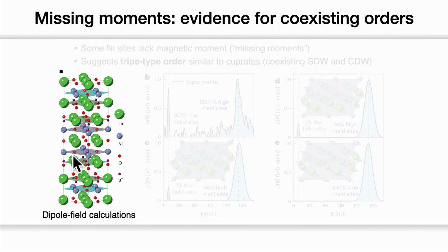Here shows the structure of the LNO superconductor. We put muons, this is a muon in purple, at some places in the material and perform so-called dipole field calculations. The reason why it is called dipole field calculation is because the spin of the muon is like a magnet, and the magnetic moments for those nickel atoms are other magnets, and they interact with each other via dipole fields.